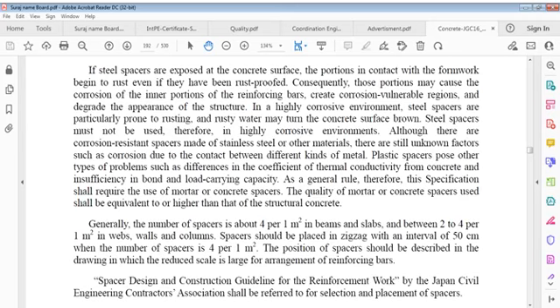Steel spacers must not be used, therefore, in highly corrosive environments. Although there are corrosion resistant spacers made of stainless steel or other materials, there are still unknown factors such as corrosion due to contact between different kinds of metal. Plastic spacers pose other types of problems such as differences in coefficient of thermal conductivity from concrete and insufficiency in bond and load carrying capacity. As a general rule, therefore, specification requires use of mortar or concrete spacers.